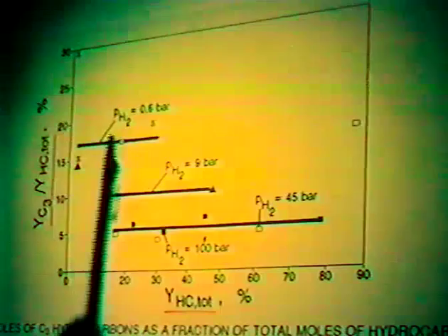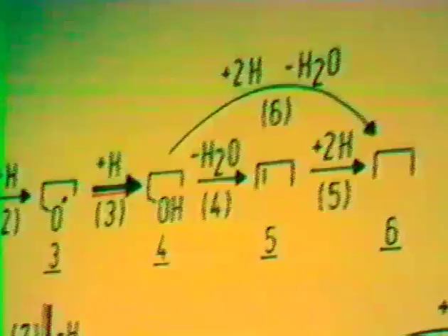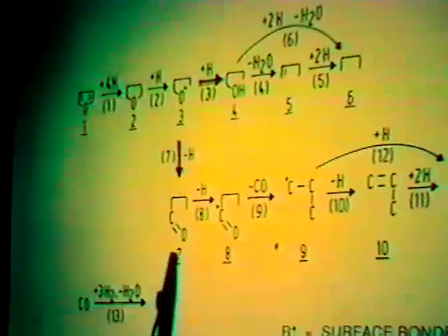So this is a reaction pathway suggestion for this small molecule. At this point we have alternative routes: it continues, as generally accepted, in the direction of butane, or it loses one hydrogen to come to the carbonyl compound, which releases the CO and yields the fragmentation to C3 and C1. So it just turns out that hydrogen availability strongly governs these systems, and we must be very aware of this when drawing conclusions.